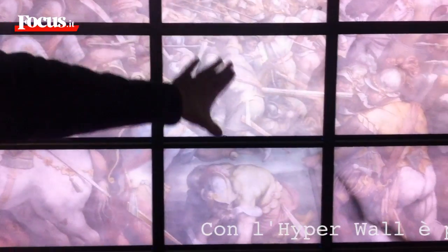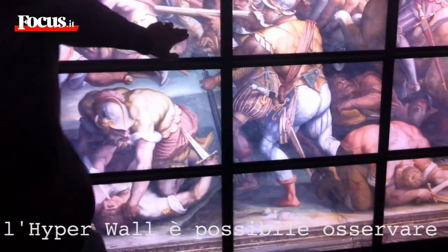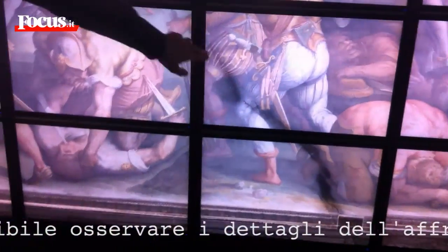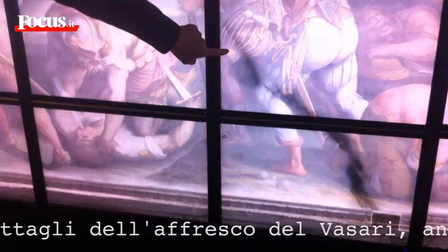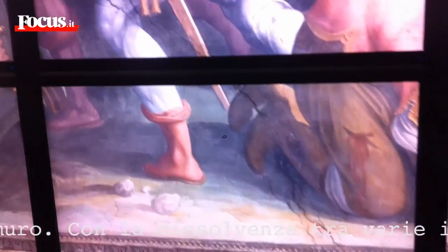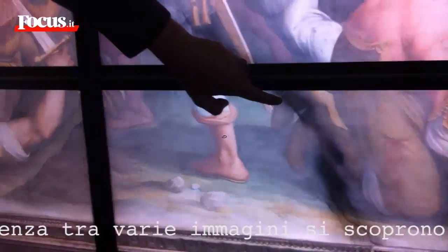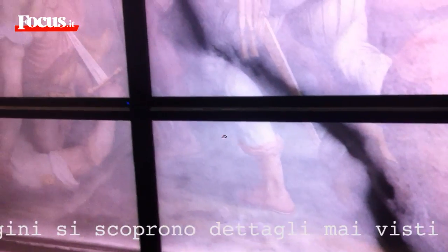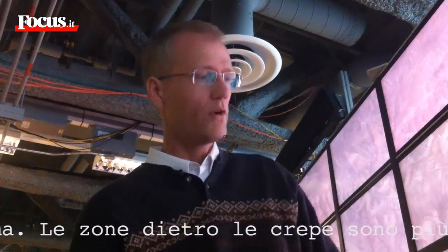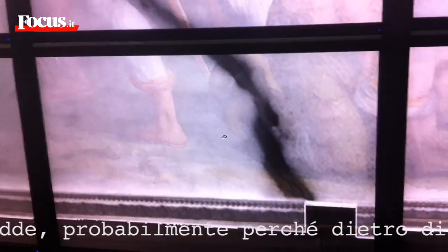Blend in and look at the thermal image underneath, which actually highlights some of the features that we see here. Now through the thermal signature, there's actually quite a bit more of a temperature variation in the areas of these cracks than we might expect from the surface. So there's a fine crack here, but a very wide thermal signature, which means there's either a very big crack behind it, or the material has detached from the surface and cold air is flowing behind it. And it turns out it's both. So there's a much wider crack behind the surface as well as the material having detached.